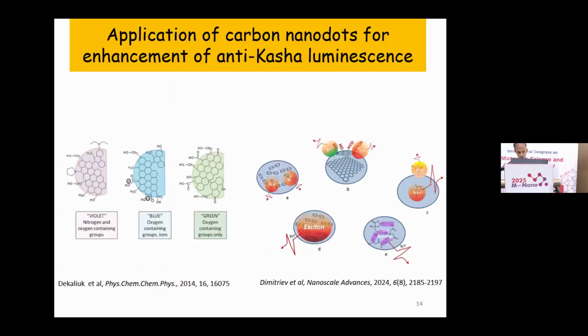The first kind of nanoparticles which I will talk about is carbon nanodots, which consist of a graphitic core, and the surface can be enriched with different molecular groups, different atoms like nitrogen, oxygen, sulfur, and so on. And this enriched surface helps us to adsorb different molecules on the surface of carbon nanodots. Also, carbon nanodots themselves possess photoluminescence. They produce photoluminescence in the blue or green region of the spectrum, and the mechanism of this emission can be different depending on the specific structure of carbon nanodots.